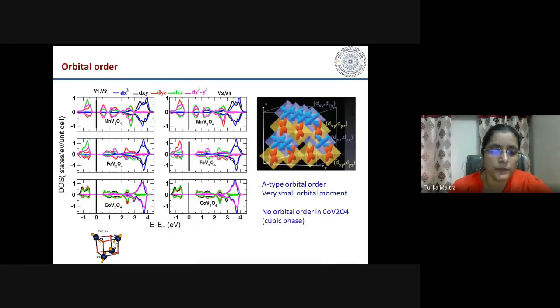So here in the vanadium we have 3+ states. So there are 2 d electrons in the T2g orbitals. So due to compression along c direction, one electron goes to the xy orbital. So xy orbital is occupied on all the sites. The other orbital can alternate between yz and xz. Okay, so this gives rise to the orbital order, and we find here that